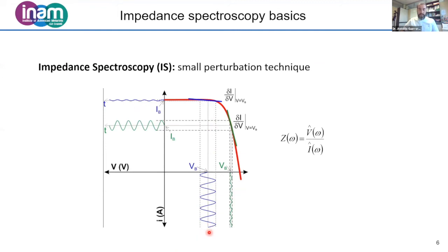Of course, we can change the frequency of this AC voltage, oscillating the voltage, and also we can change the applied DC bias. At this point the solar cell will be operating, and recombination resistance versus photocurrent will have some values, but in this region the operation mechanism could be different. For example, here the recombination current is higher than in this part. But we can do the same thing: we change the DC bias, we apply the small perturbation voltage, and we measure the current.